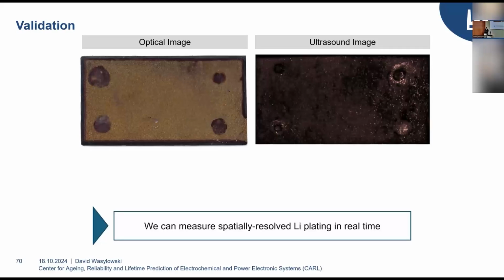So in conclusion, we can measure spatially resolved lithium plating in real time, and this can obviously be used to design fast charging algorithms. So without any prior knowledge of your battery cell, you can just start charging it, make these ultrasound images, and when you see this indication happening during the fast charging process, you would tune down your charging current, and very quickly and without really any prior knowledge of the cell get to a semi-optimal charging procedure, which might actually also accelerate the development process of charging processes.